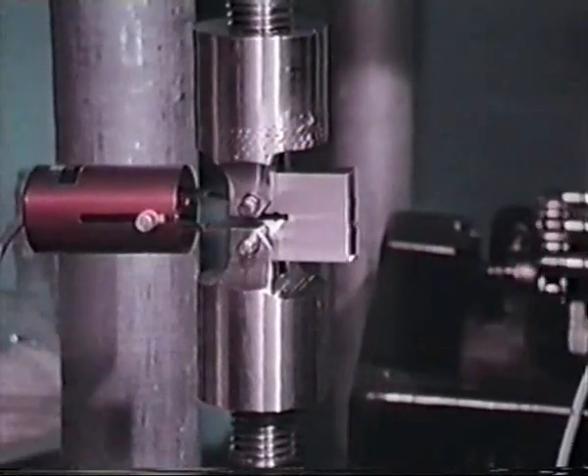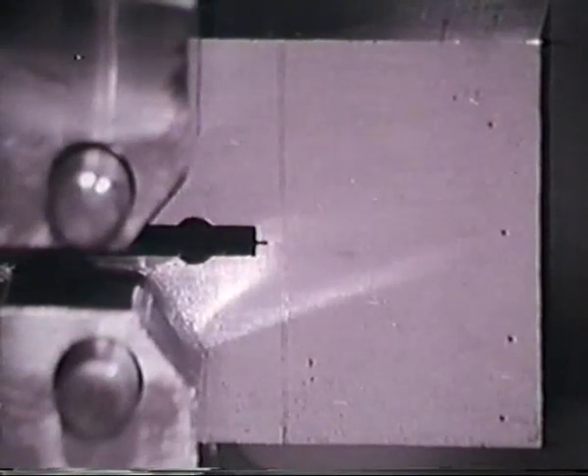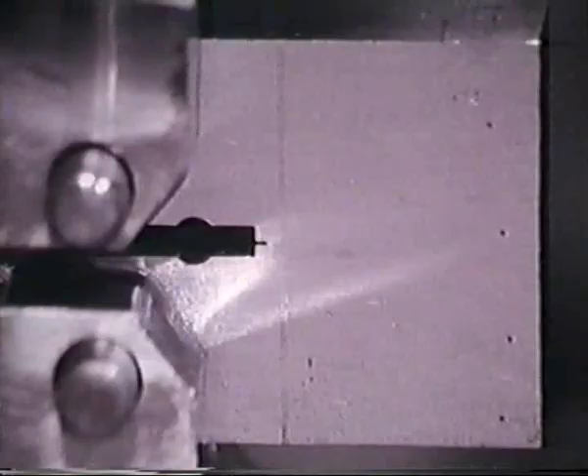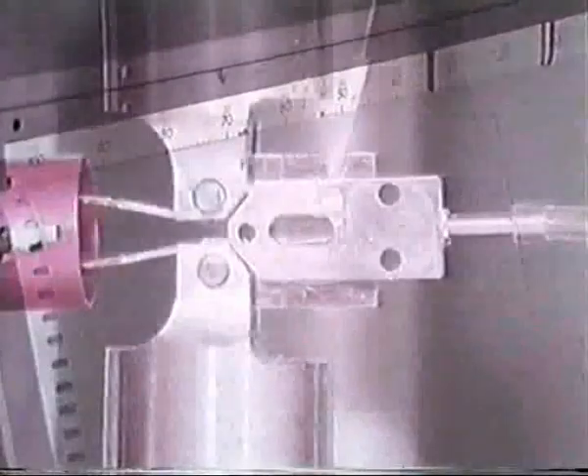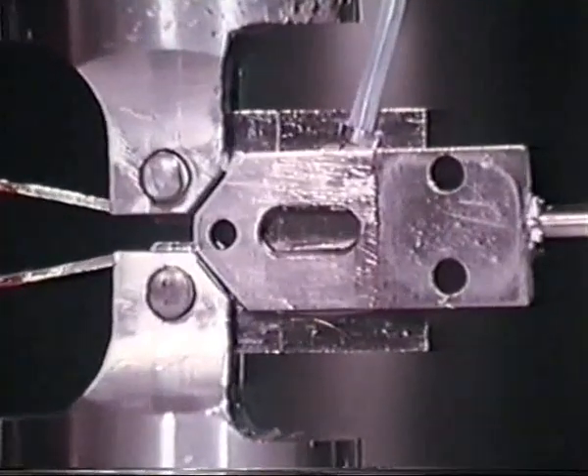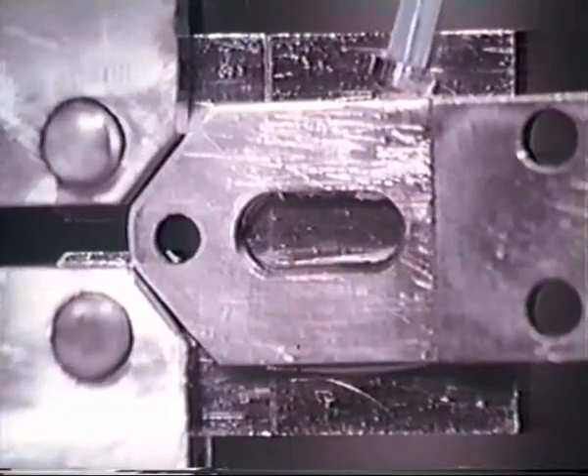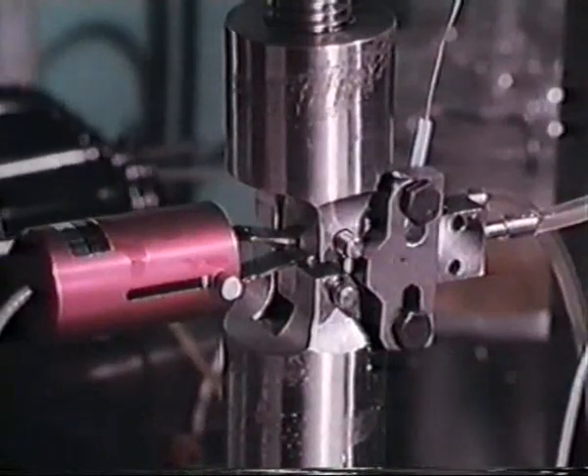Put in tension, the opening of the crack is measured with a transducer. In a non-corrosive atmosphere, the crack opens slightly as the load is applied, but does not grow any further. A similar specimen is then surrounded by a cell which is to contain the corrosive medium circulated by a pump. When the corrosive is introduced, the crack starts to grow. Eventually, assisted by corrosion, the specimen breaks under a load it had previously withstood.